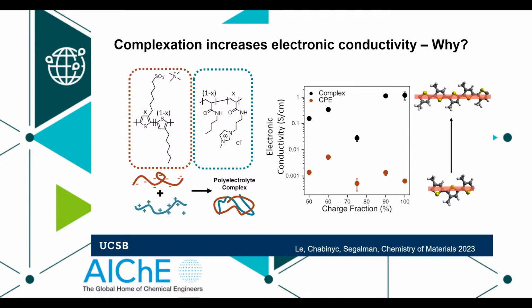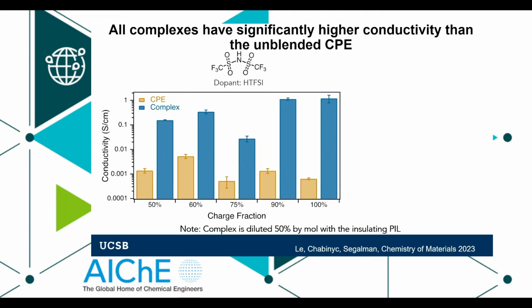See that all of the complex dots, the black dots, are a couple of orders of magnitude higher than the polymer from which we made it, right? On my best day, I might try to convince you that's because the chain stretched out and I got higher conjugation length. But even on my best day, 2 to 3 orders of magnitude is a huge improvement. It's probably not just that.